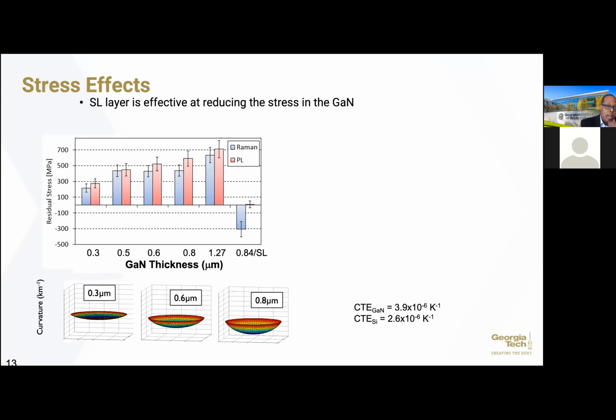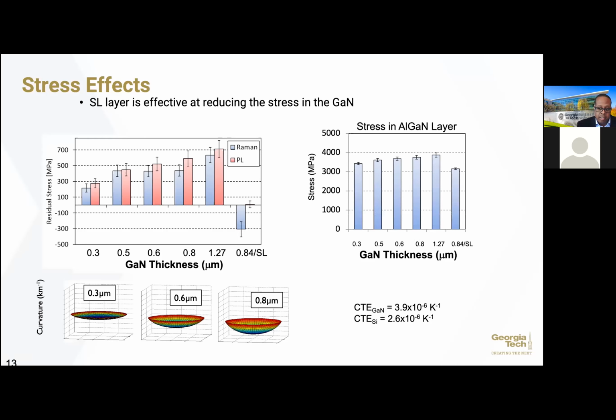The other thing that we do worry about is that the AlGaN layer, which is about 20 nanometers right on top, undergoes what's called pseudomorphic growth, which just means the lattice of the AlGaN takes on the lattice of the gallium nitride. It's stretched. That's all we need to know, is that it's going to be under a tensile stress. And so we're basically now just calculating what the stresses are in the AlGaN layer and how it drops when you get to this pseudomorphic growth on top of this superlattice structure. And so these are things that are very, very interesting for us to go through to improve the overall reliability of the devices from a mechanical point of view.